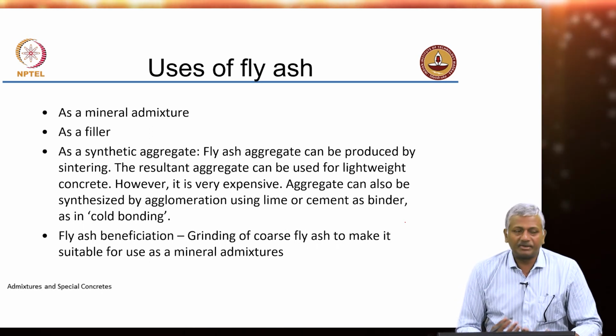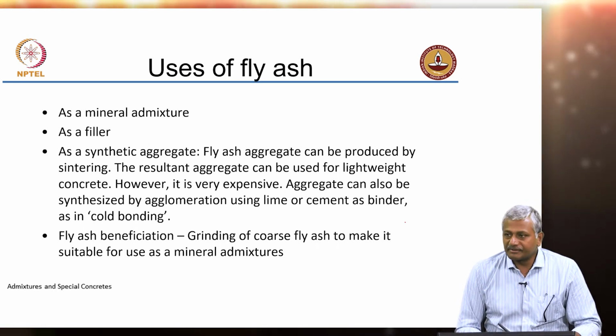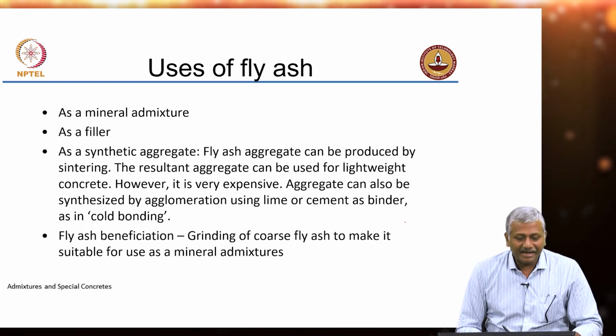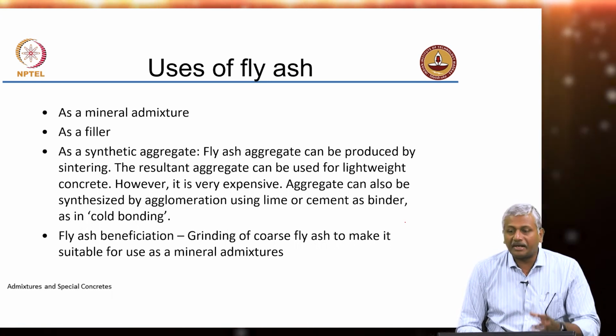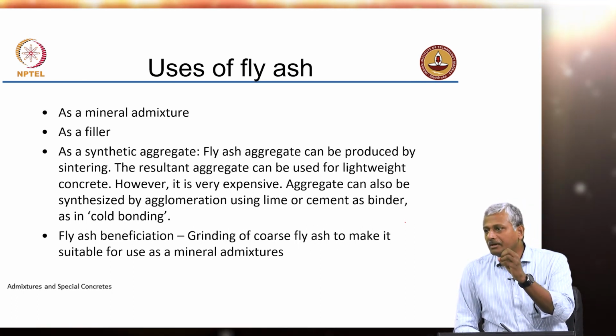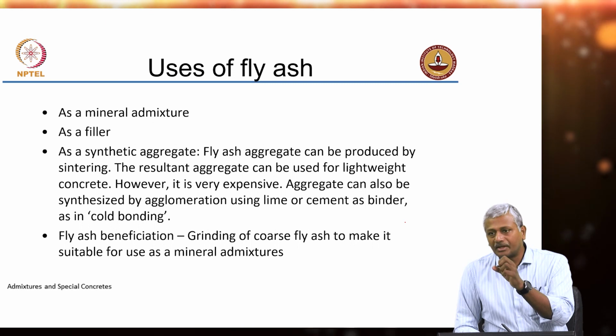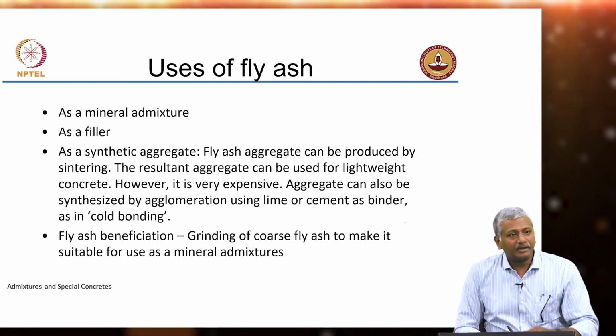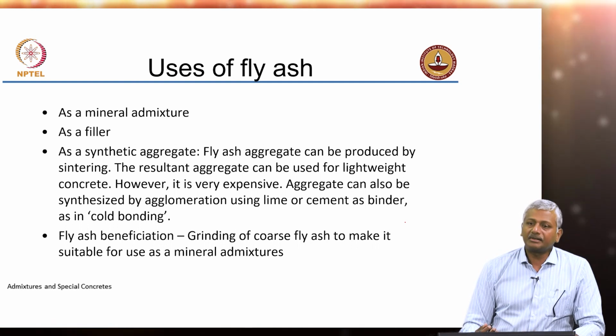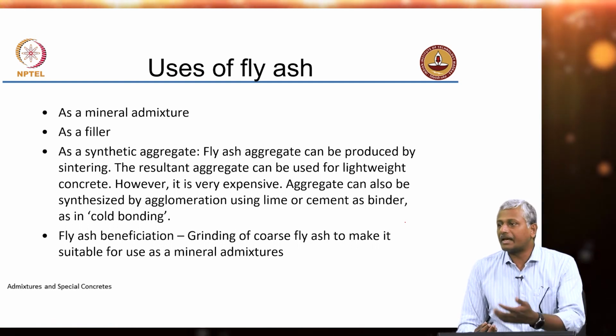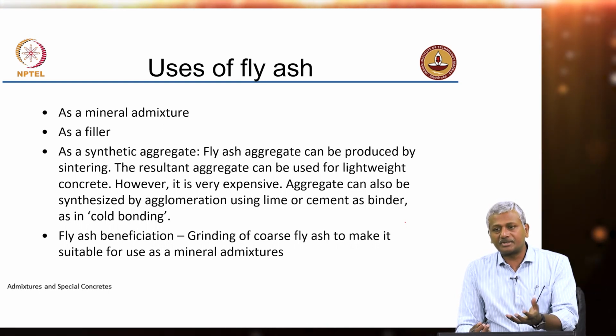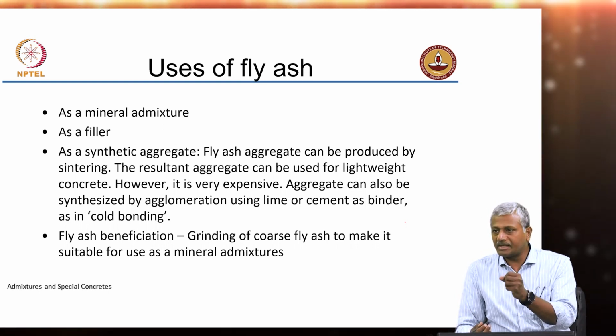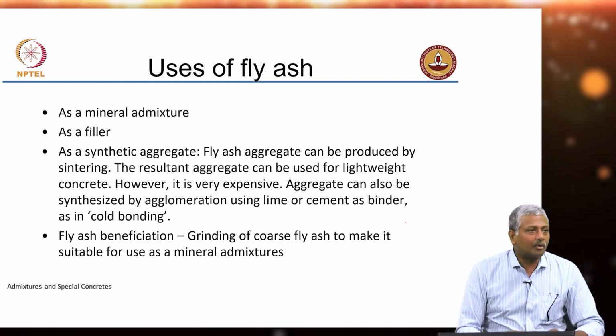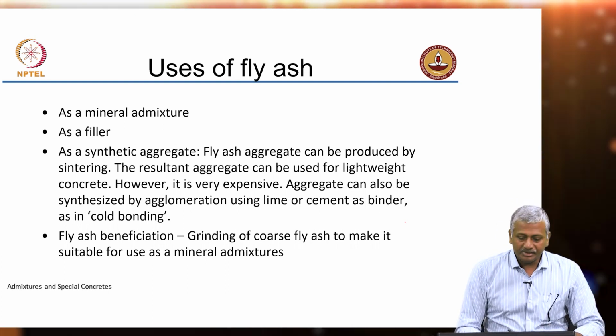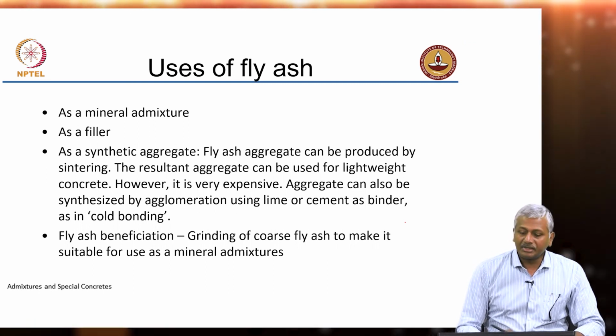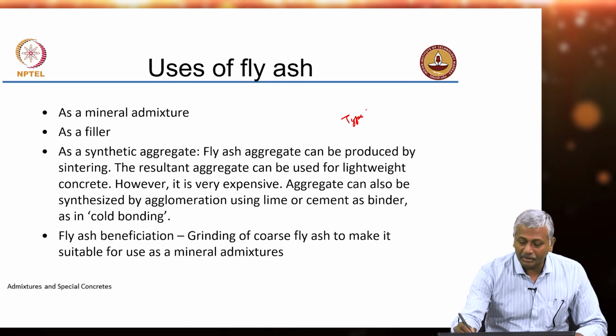Now, fly ash, as I said, we use it as a mineral additive, we could also use it as a filler. Fly ash can also be used as synthetic aggregate. There is significant research that shows that pelletization of fly ash, that means making aggregate size pellets from fusing the fly ash particles together and then sintering at high temperatures, or bonding it through means of hydration. For instance, in type C fly ash, there may be sufficient calcium in the system, so that the hydration can actually bond these pellets together. So, you can form pelletized fly ash particles which are good as aggregate. So, sintering can be done for type C fly ash, type F fly ash.